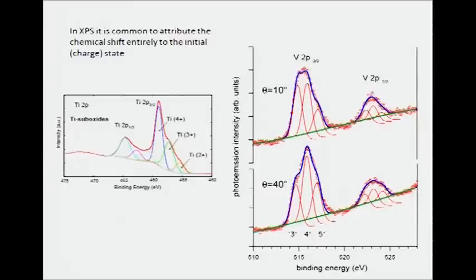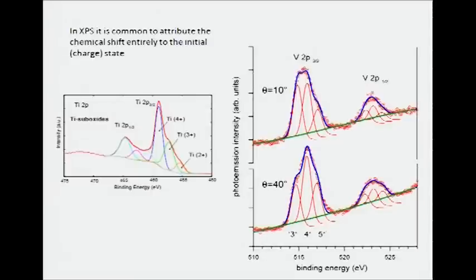So here, this, for instance, is the titanium 2p spectrum from some titanium suboxide. You'd just expect a doublet, but you see there's a whole series of peaks, and the labeling you notice is just Ti4+, Ti3+, Ti2+. It's a labeling that implies that the dominant reason for these shifts is the initial state, the ground state, the one electron binding energy of these states. And I just show on the right some slightly more recent data, which is actually from a vanadium titanium oxide. And you see exactly the same thing in the vanadium. You see these multiple states, which you can put these simple labels on. But it's really not the whole story.